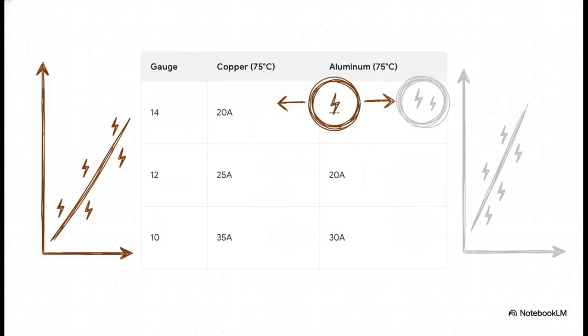To really wrap our heads around these two metals, we have to look at the very clear performance gap between them. So check out this data from Southwire. It shows the safe continuous current, which we call ampacity, for different wire gauges at 75 degrees Celsius. Notice how a standard 12-gauge copper wire, the exact kind sitting inside your home's walls right now, can safely carry 25 amps. But if you look at the exact same size in aluminum, it can only handle 20 amps. And it's the same story at 10-gauge. Copper handles 35 amps compared to aluminum's 30. So across the board, copper just consistently carries a higher load safely.